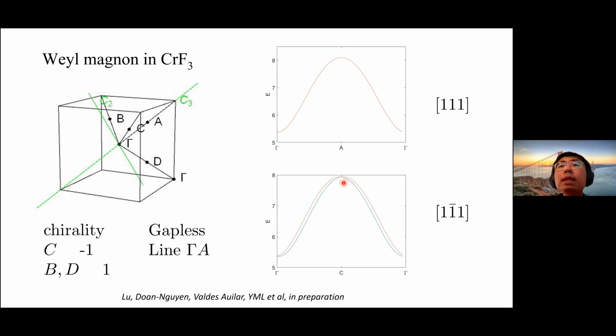The splitting of these two bands leads to a Weyl point, a band touching between these two bands. These Weyl points are going to lead to surface Fermi arcs in the system. So this is what happens in chromium trifluoride.